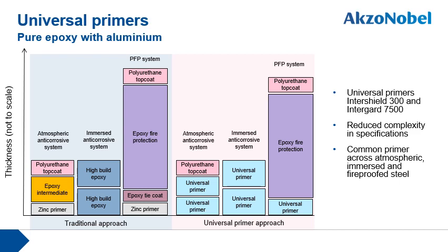The graphic on this slide shows a comparison of the complexity of the traditional specification approach, which you can see with the slightly blue background, where 6 or 7 different products were needed to do the job just for ambient temperature exposure. This is in contrast to the universal primer approach, and that's what you see with the slightly pink background here. And this is where a single primer is used, a primer such as Intershield 300 or Intergard 7500. And all you need is a polyurethane top coat over it for atmospheric exposure or UV exposure, or in the case of a fire protection system, then you apply the fire protection product directly over the universal primer. So this significantly reduces the number of products that you need to protect both structural steel as well as immersed steel.